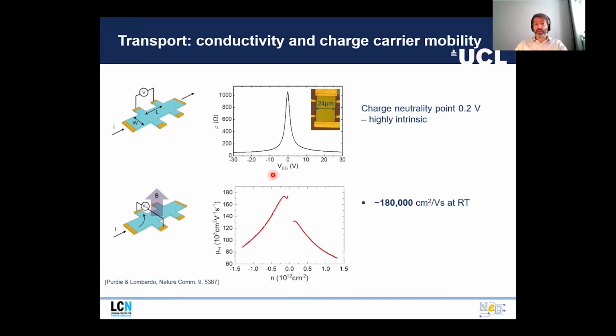We also measured the mobility as a function of the charge carrier concentration in the presence of a moderate magnetic field. And we achieved very high mobility at room temperature, in the order of 180,000 cm^2/V·s. And this mobility, as expected, went much higher at low temperature, where it approaches about 2 million. What is also important is that the disorder-induced charge inhomogeneity was very similar to suspended samples.